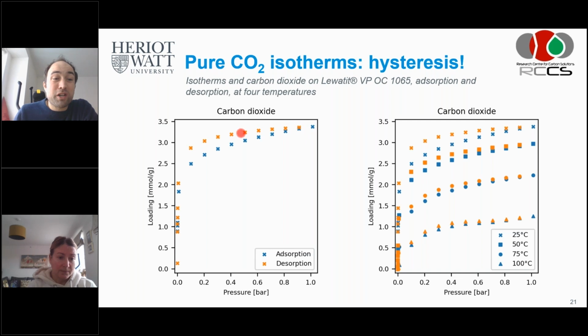But reduction of that pressure only is apparently not sufficient to reach the same loading again as you had at the adsorption branch. So that would imply that there is a barrier somewhere. And that barrier may be in blocked pathways because of channels or pores closing. That is a very real possibility in this material because it's a polymer resin, and we know that this kind of behavior happens with polymer resins. The alternative explanation is that you indeed need to go over an energy barrier.